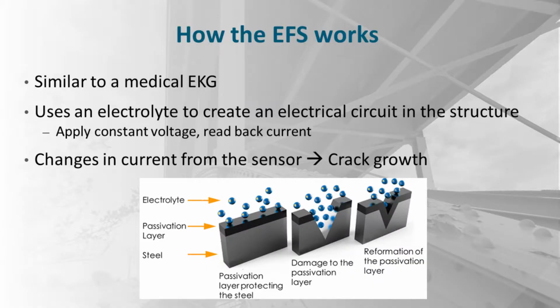What the sensor reads back is once this passivation layer has been broken or stretched out. As you can see in the second part of that figure, a crack has been formed. When a crack has been formed, new steel is being exposed. That makes the electrical signal change significantly. And once it's been exposed, the passivation layer reforms again. And this goes back and forth, back and forth. The passivation layer breaks when you have a significant loading and the crack is growing, and reforms again when the load comes back to what it was.